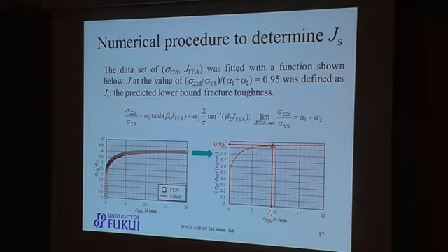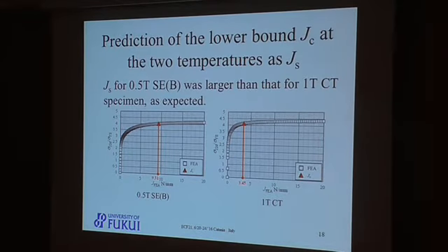Since there is not a definite method to determine the converged value of σ22d, here we applied the following method. First, the data set of σ22d and JFEA was fitted with a function shown here. Then, J at the value of normalized σ22d over the converged value of α1 plus α2 equal to 0.95 was defined as JS, the predicted lower bound fracture toughness. By using this method, the predicted values of JS were obtained as 9.35 and 1.45 N/mm for these specimen types respectively.